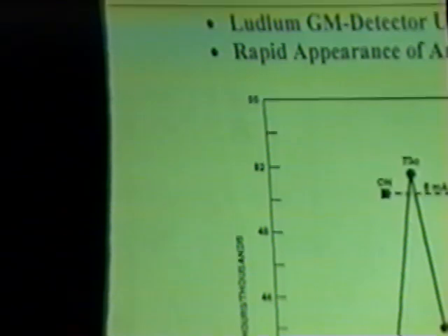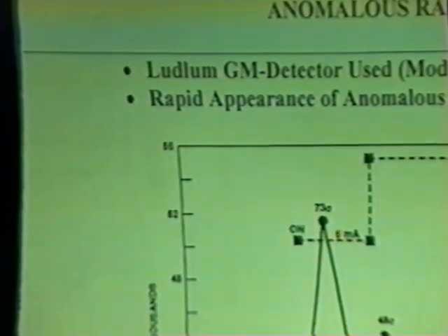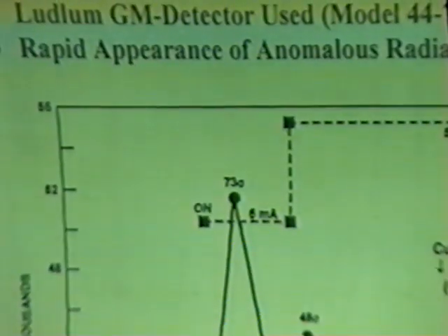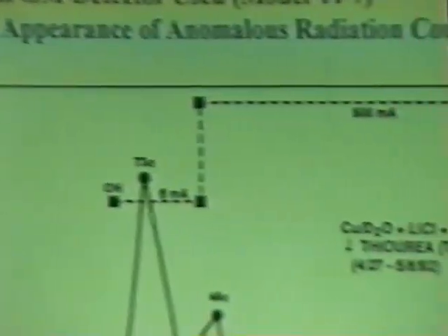We only had 6 milliamps running through the cell because we're depositing palladium. We wanted to do that rather slowly, so it's a low current. Under these conditions, you'd plate out all the palladium in about 24 hours that was in the solution.